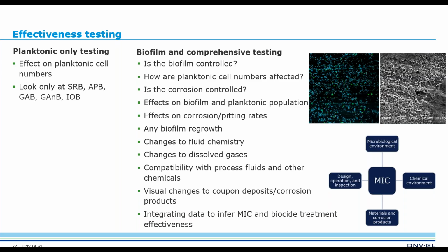The effect of process chemicals like drag reducing agents and oxygen scavengers on biocide effectiveness and mix should be tested. Any visual changes to the coupon in terms of deposits or corrosion products are also important to consider, because that can help understand the corrosion mechanism and if there are any other changes happening in the system. And once all of this information is collected, this data should be integrated to infer the effectiveness of biocides in preventing and mitigating MIC. Next slide, please.